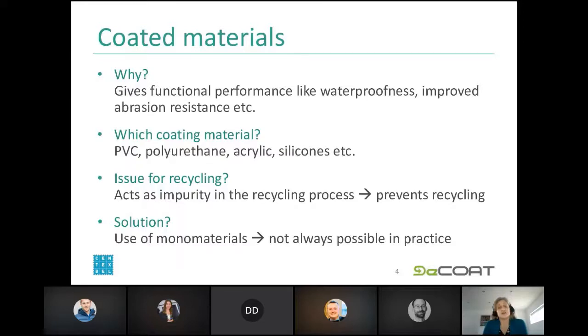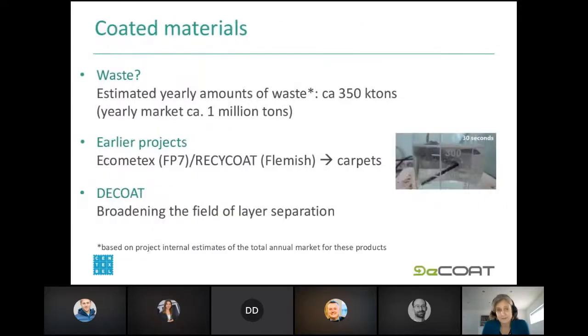A first solution is that we would produce these materials as monomaterials, meaning that the bulk material and the coating will consist of the same material. For example, a PE fabric with a PE coating. But this is not always possible in practice because often the functional requirements are not met if we compose the materials in this way. We estimate that every year around 350 kilotons of waste is generated, so there are quite huge amounts. At Centexbel, in the past, there have been some projects running to deal with these materials.